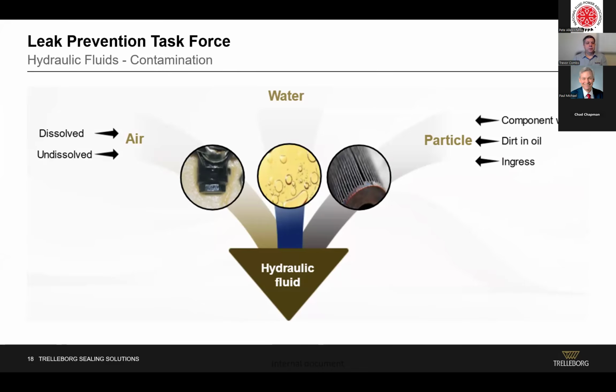And then lastly, for fluids, contamination is really key. I think a lot of failures are due to oil contamination. And as you can see on this graph, contamination can come from a lot of different sources. I think we typically think of contamination as just particles getting into the system. But it's a bit more than that. It can start with a dirty oil, or maybe there's water or air that got into the system, whether it's dissolved or undissolved air that can affect the sealing, the seals, and the leakage prevention.